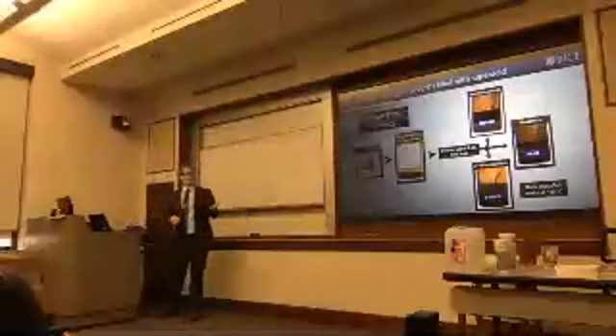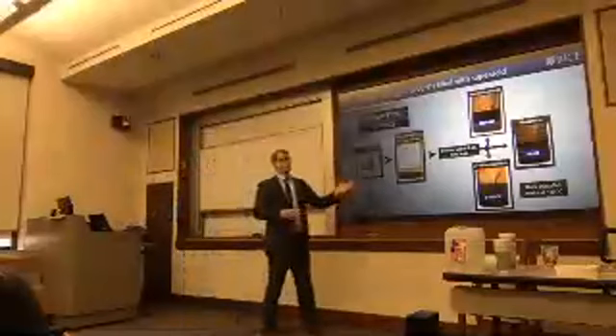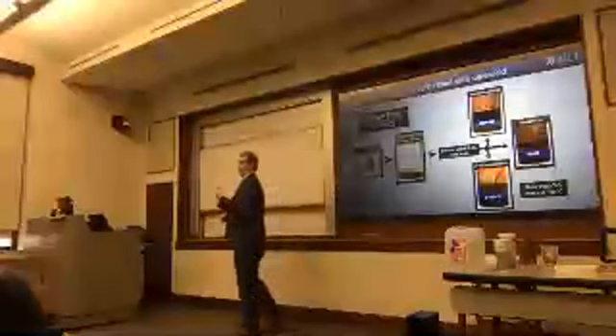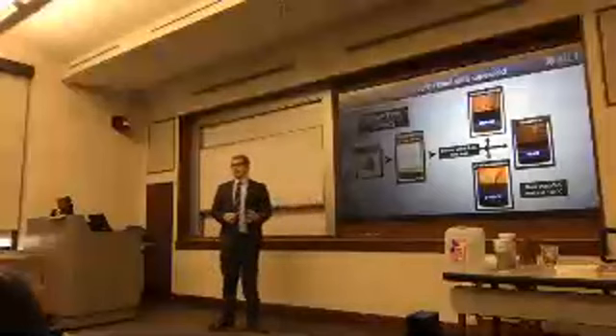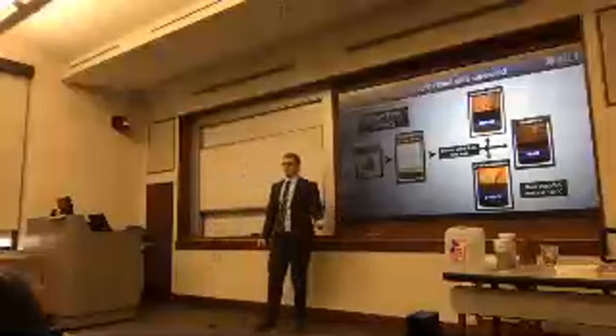So that's promising already. So going forward, we'll denote these with a little shorthand. We'll call methane sulfonic acid MSA, phosphoric PA, and paratoluene sulfonic PTOS. And we'll denote that it was dissolved by this oleum first strategy, OF. And at this point, I need to note that PTOS is actually a solid at room temperature, but it melts very easily by heat gun at 40 degrees Celsius.